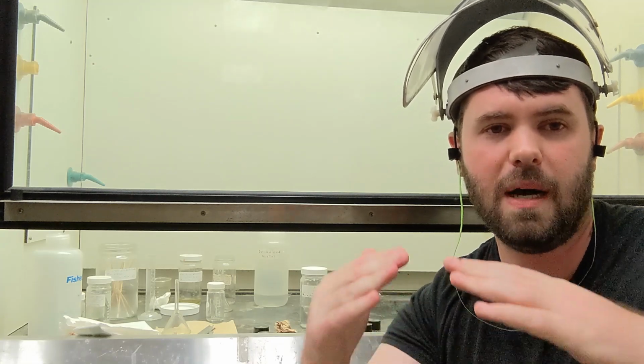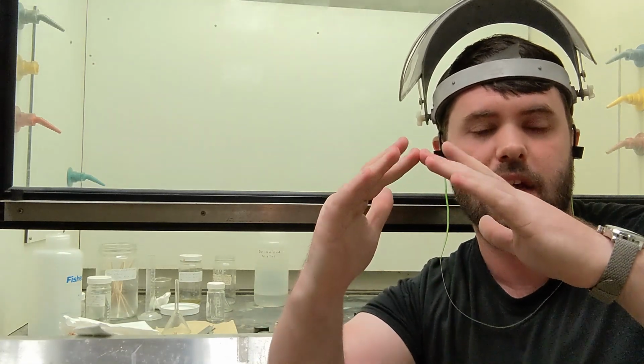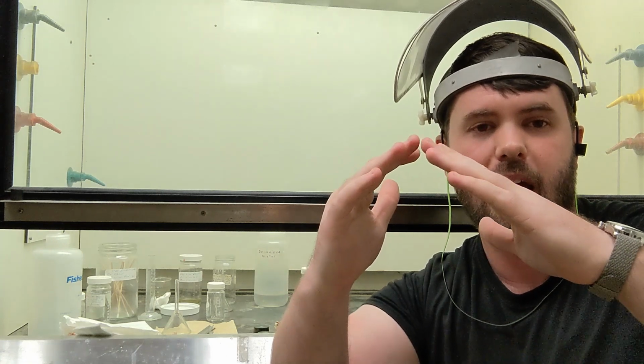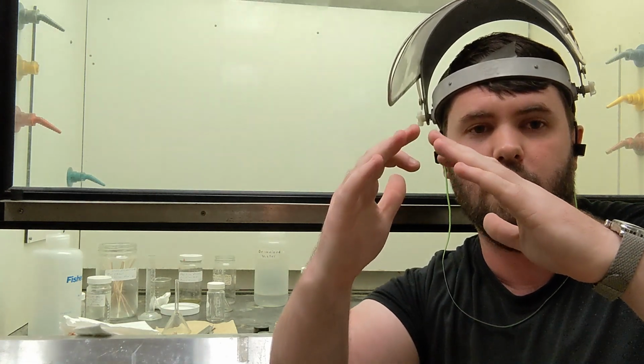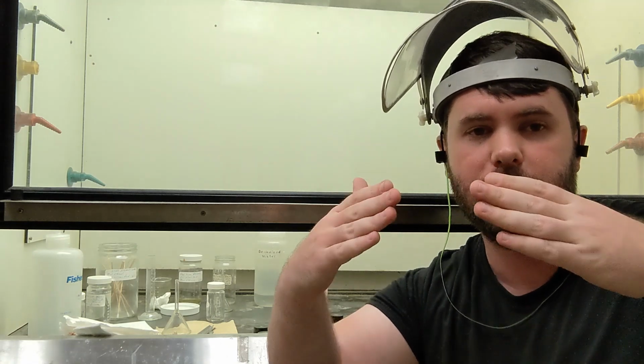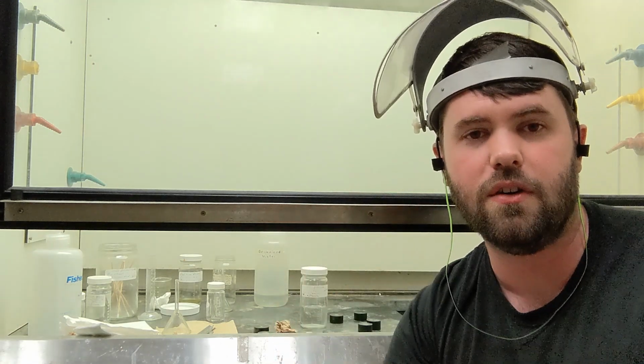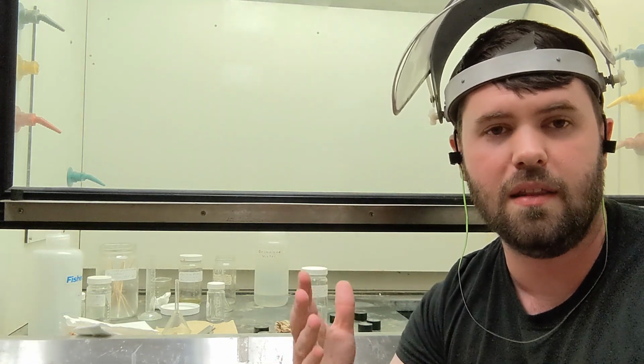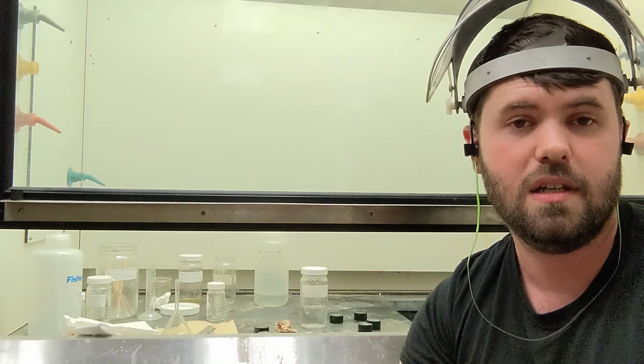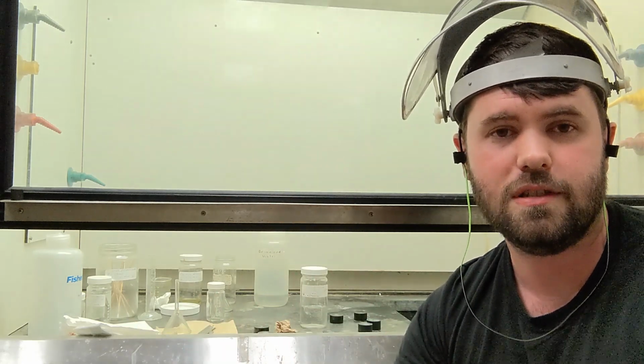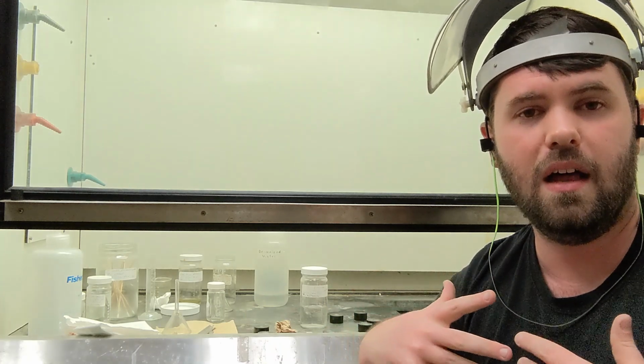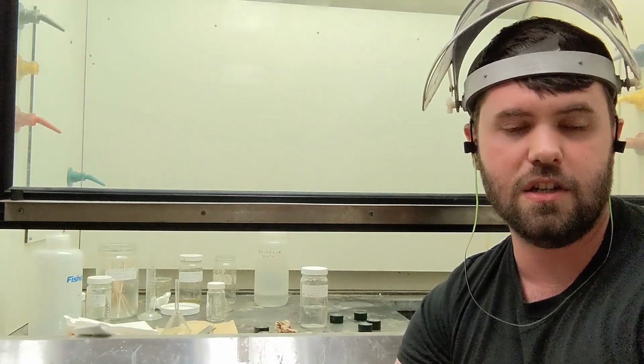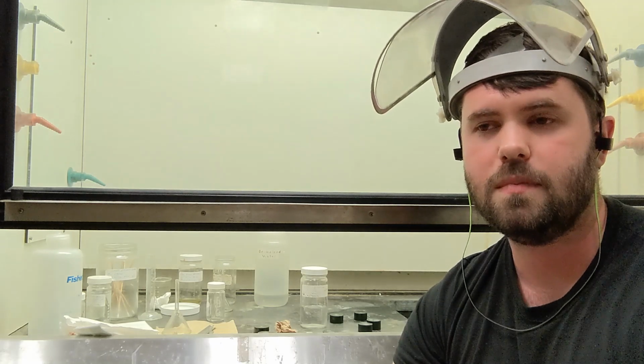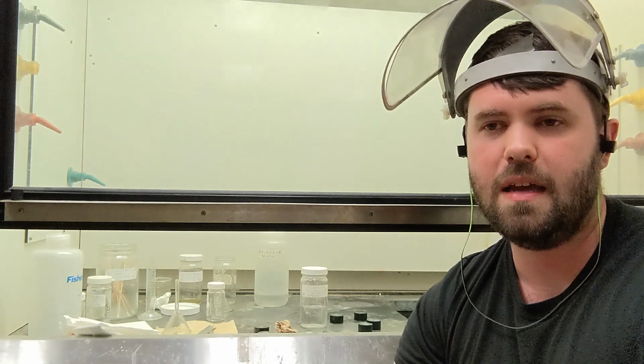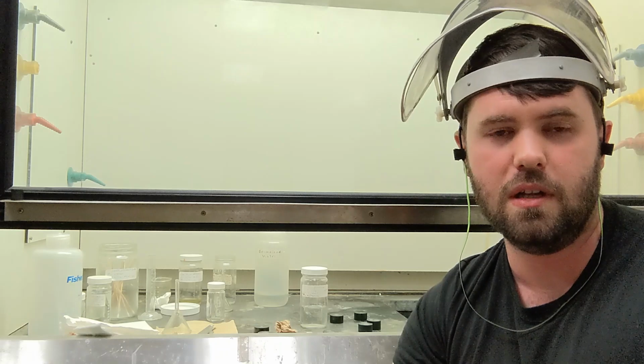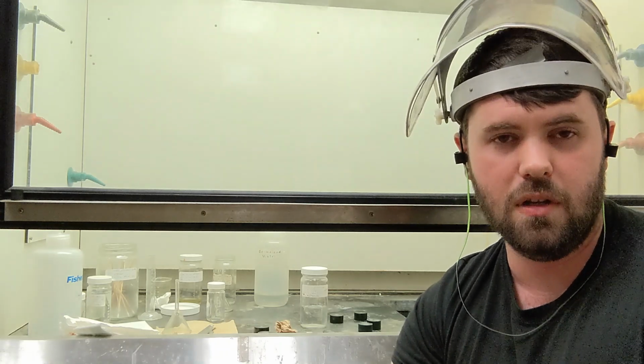So by attacking these atoms that are at these angles, you basically remove the atoms at the tip, and by slowly removing them, you will widen the grain boundary and dig a sort of trench into the material. And what that will show up in the microscope is dark lines identifying our grain boundaries. So for steels, the most common etchant is an etchant known as Nital. Nital, N-I-T-A-L, is a mixture of nitric acid, 2 milliliters of nitric acid, and 98 milliliters of ethanol.